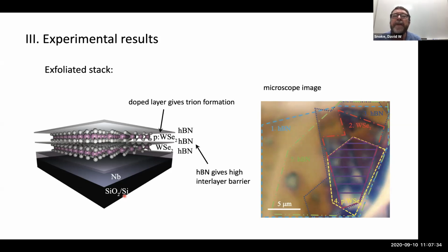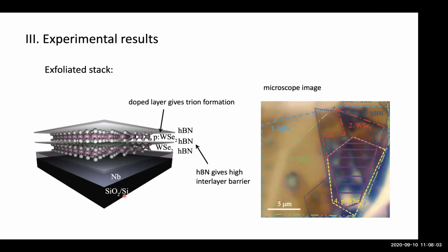It shifts them. The binding energy of the exciton is like 80 to 100 millielectronvolts. And the exciton is neutral, remember, so it's not strongly changed by image charge because it's just a neutral image charge interacting with the neutral exciton. That is shifted by maybe 5 to 10 millielectronvolts, and the trion is shifted maybe 10 to 15. So there is an effect. It's not a huge effect. Okay.